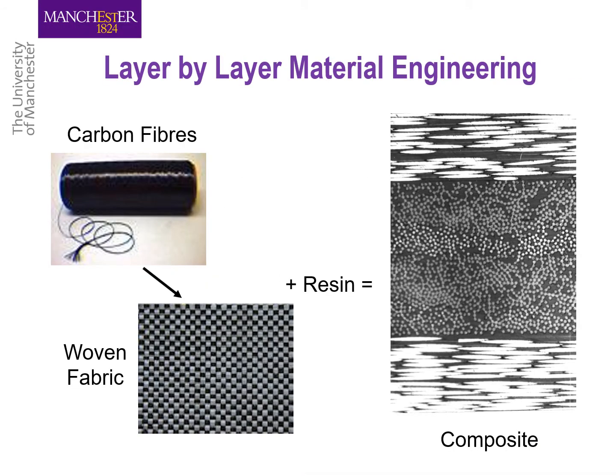So we spoke about hybridization, where we mix layers of metal and layers of composite. We spoke about hybridization at the fiber level, where we protect the stiff and strong glass fibers with softer polypropylene fibers that also enable us to have some kind of self-healing process upon heating the laminate. We spoke about interleaf toughening, where we introduce thermoplastic veils at critical interfaces where delamination is expected. And there is another way of introducing toughness or making it harder for those cracks to be triggered. And this time we bring in graphene into play, where the more brittle epoxy resin is nano-modified with graphene platelets.